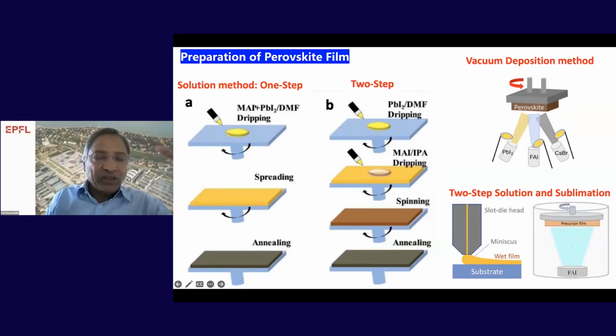In this method, we have methyl ammonium, that's an organic cation, and lead iodide, in a particular solvent like DMF or a DMF-DMSO mixture of solvents. You dissolve this composition in these solvents and then spin coat it and anneal it, and you get the perovskite films. In a two-step process, first we deposit lead iodide, followed by methyl ammonium iodide and annealing. So this gives you the perovskite films.